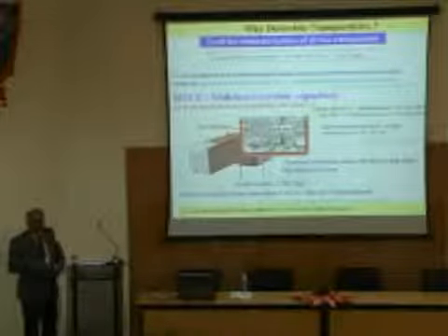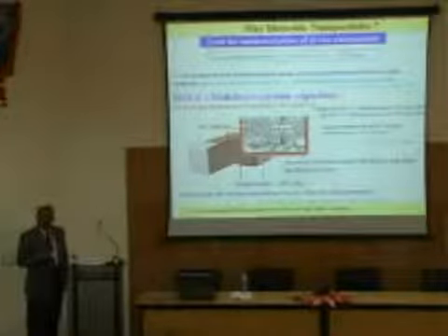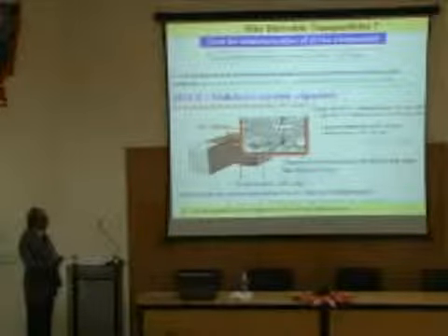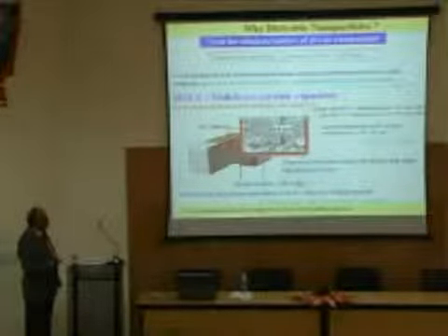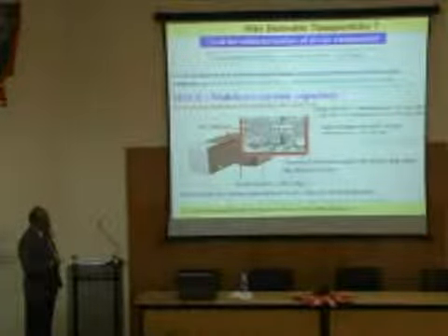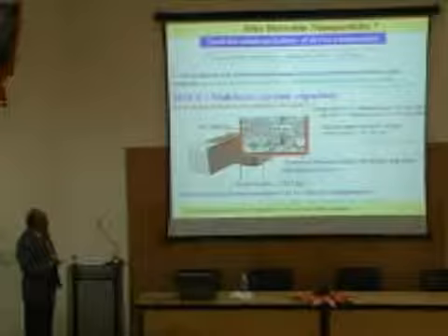Okay. I will talk a little bit about dielectric nanoparticles because a lot of engineers are there. As you know, dielectrics are very important, and barium titanate is a very important dielectric material for multi-layer ceramic capacitors. This is a multi-layer ceramic capacitor where you have barium titanate and then metal layers embedded inside. If you take a cross section of this in a SEM, scanning electron microscope, each layer is of the order of 0.9 micron.